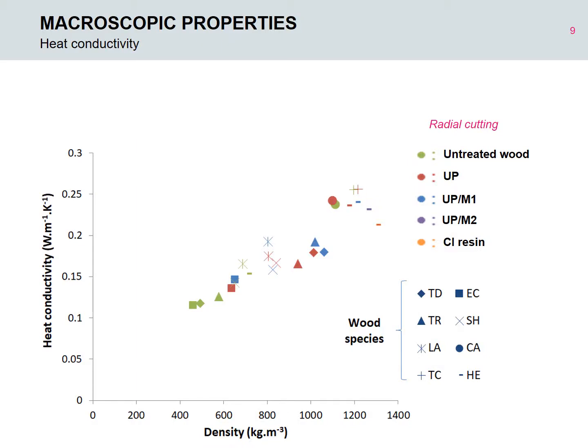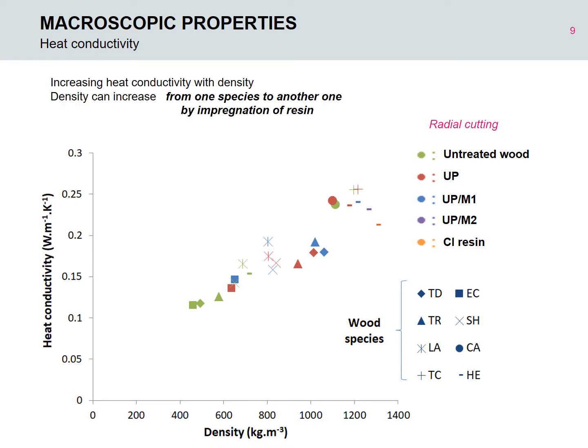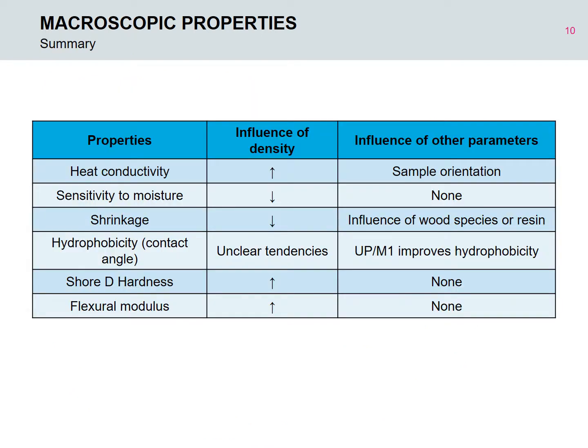About macroscopic properties like heat conductivity, here the main observation is that the density of our wood plastic composites controls these properties. For example, here heat conductivity increases with density, whichever the wood, whichever the resin incorporated into the wood. This observation can be extended to other macroscopic properties like sensitivity to moisture, shrinkage, or mechanical properties. In all cases, the density is the main parameter controlling these properties.